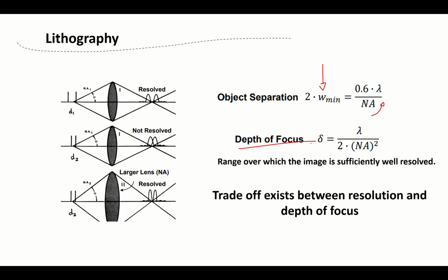However, there's a concept called depth of focus. It's the range that can be tolerated for the image to be resolved. If this value becomes low, the process will be really difficult, since the acceptable range for a wafer to move up and down is really limited, and it will be hard to focus for the resolution. So if you increase NA, depth of focus decreases, which will be a challenge for the process, but you also increase your resolution. So there is a trade-off between resolution and depth of focus.